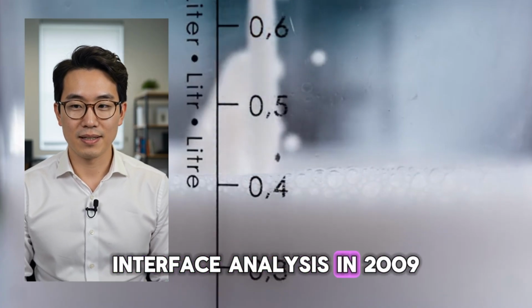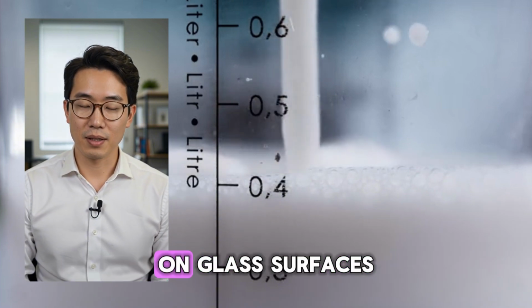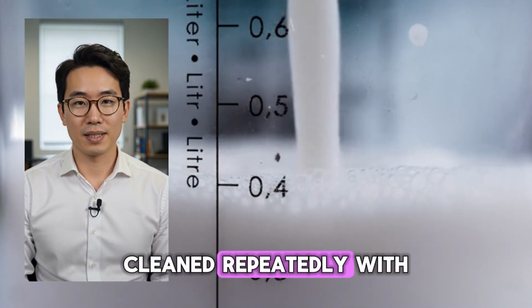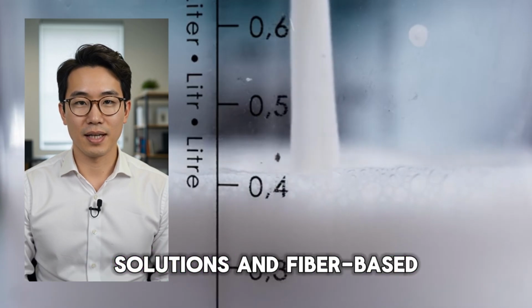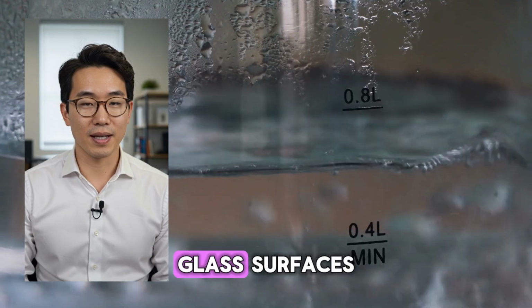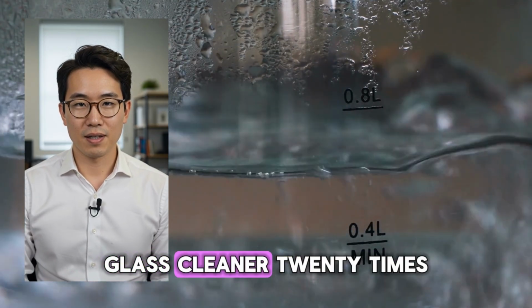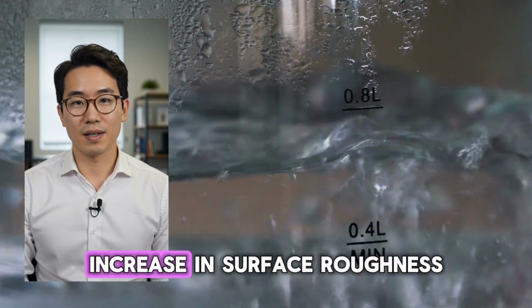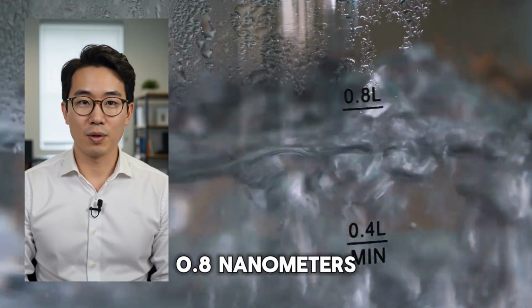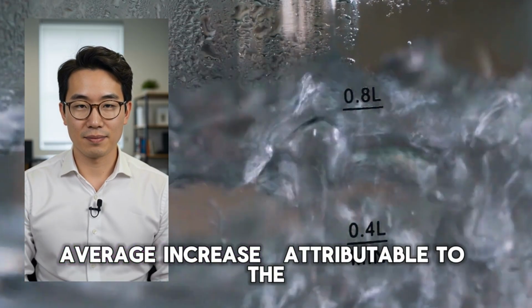A study published in the journal Surface and Interface Analysis in 2009 characterized the polymer and surfactant film accumulation on glass surfaces cleaned repeatedly with commercial glass cleaners versus surfaces cleaned with acidic solutions and fiber-based wiping media. Glass surfaces cleaned with commercial glass cleaner 20 times showed a measurable increase in surface roughness, 0.8 nanometers average increase, attributable to the accumulated polymer film.